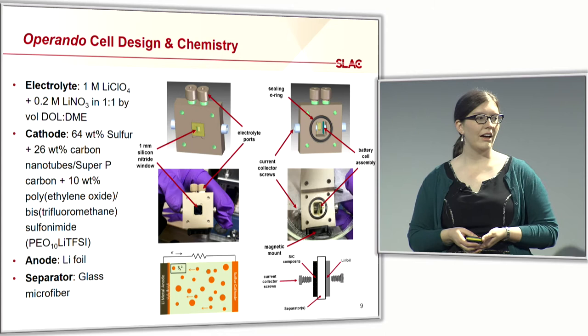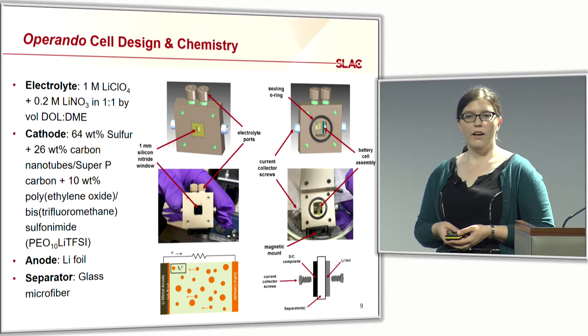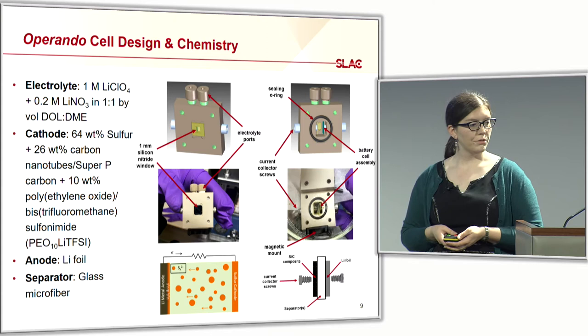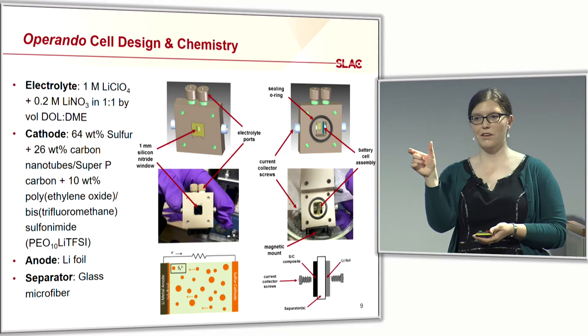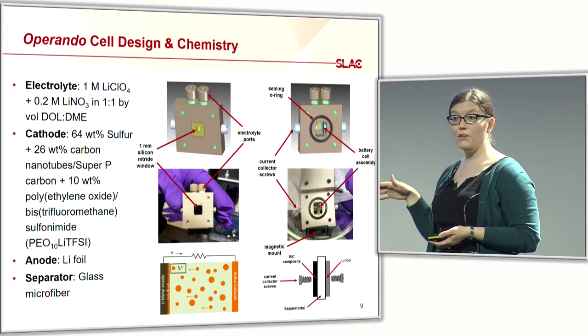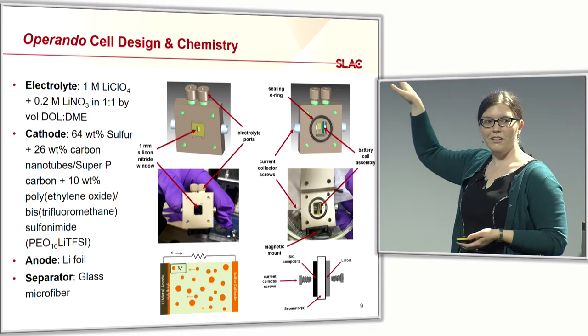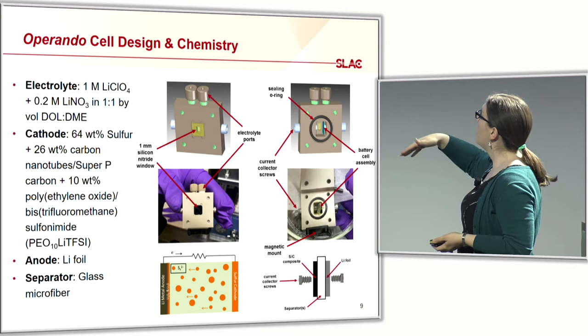That led me to design a more robust cell with a better-defined geometry so I can repeat the experiment and compare apples to apples. I used the same lithium perchlorate system and a next-generation sulfur/Super P/carbon nanotube/PEO/LiTFSI cathode, lithium foil again, and a glass microfiber separator to maximize the electrolyte area. I'm using a one-millimeter silicon nitride window as my field of view to get a very large field of view. On the right-hand side you can see the innards of the cell — I build the battery directly into the cross-sectional cell and have two current collector screws on either side.